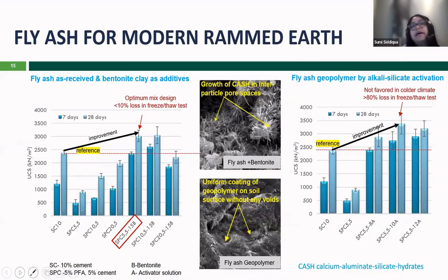So I'll summarize what we have achieved from all the tests in two combined pictures, because there are tons of data to share, but I'm just going to summarize them as a whole so that we can understand the overall outcome of this rammed earth work. So we have used the fly ash as received, and we have used some calcium bentonite clay as an additive, and we have looked into the UCS data, unconfined compressive strength, for several combinations.